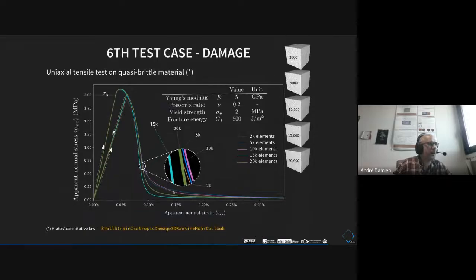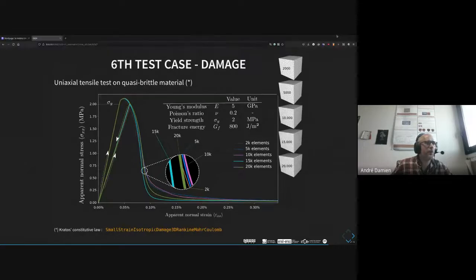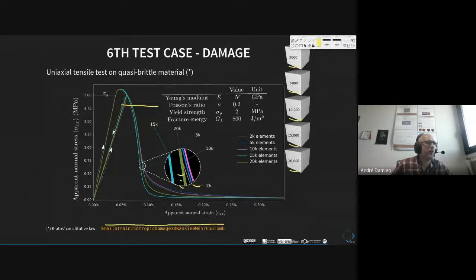And the last thing is about the quasi-brittle material. We introduce, in fact, damage modeling inside the material. And here we put a yield strength and a fracture energy, and we get this answer, which is quite in line with what we would like to expect. Just the post-peak behavior is quite different. I don't know if it is significant or not, depending on the number of discrete elements inside our sample.